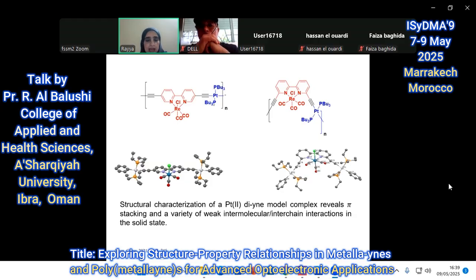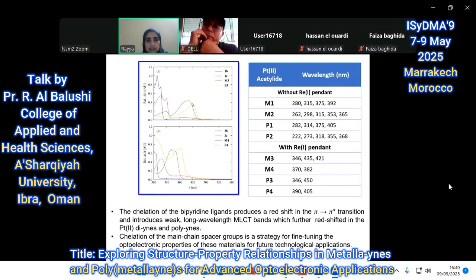So these are heterometallic systems, and we observed that the photophysical properties are better by having the second metal. We measured the photophysical properties as shown here. Here it is without rhenium, and the data below are with the rhenium. As is clear here, there is a red shift in the properties. So it indicates that the chelation of the bipyridine ligand produces better photophysical properties. Why do we say it's better? Because once we have a red shift, we have a smaller band gap, so it is more useful for applications such as light emitting diodes or solar cells.